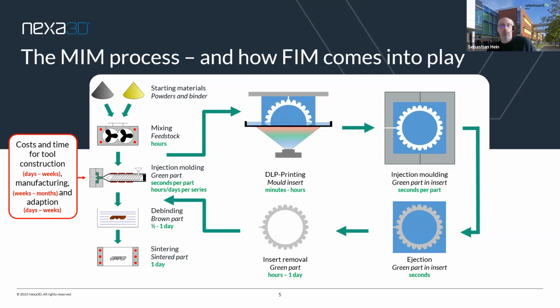As Lasse mentioned, the most important aspect here is the dissolution of this material, which gives you the opportunity to have any kind of undercuts that you would not be able to eject, because it is just geometrically not possible. And then you can see this is really done in a matter of hours to a day. So basically, the dissolution of the mold is the longest aspect of this chain here if you introduce it.